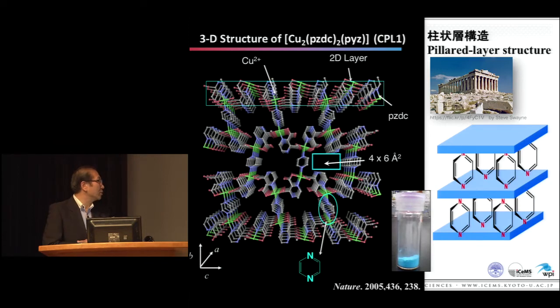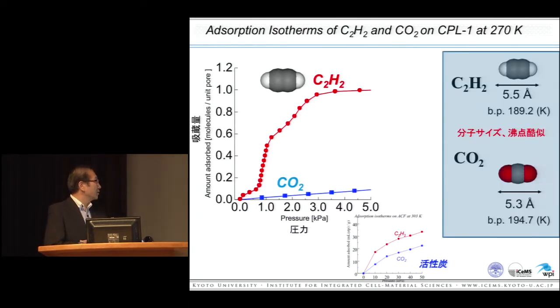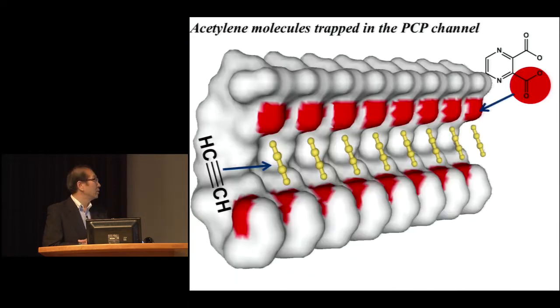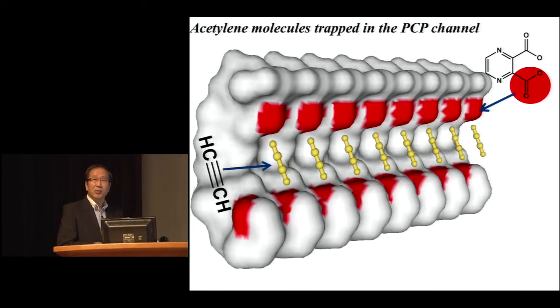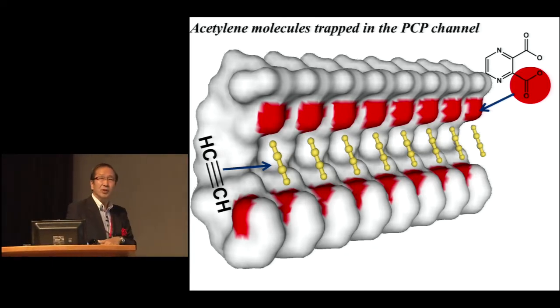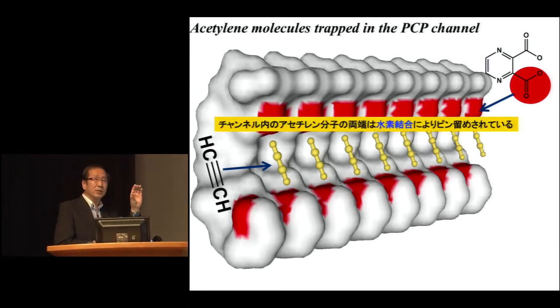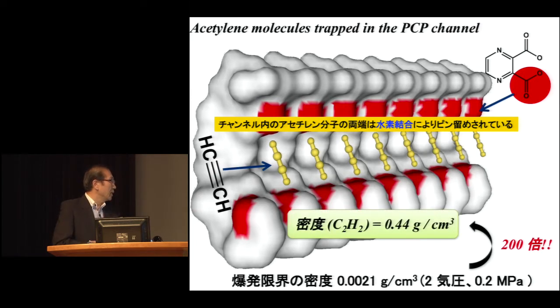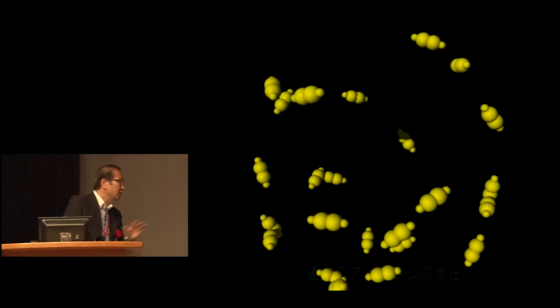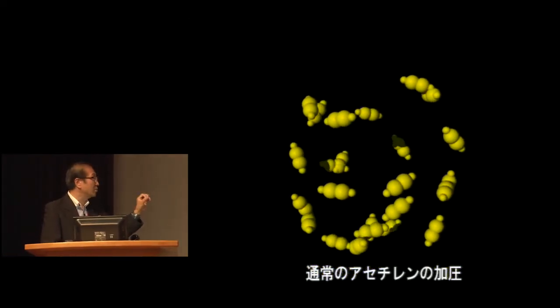This is the pillar layer structure we used to store acetylene more safely. That is the crystal. This is pressure by amount absorbed. The structure is very similar between acetylene and CO2, but only acetylene can be absorbed because of this structure. As you can see at the cross section of the pore, there are double hydrogen bonds. The hydrogen bond which can be seen in water. So double hydrogen bonds were used to pin down acetylene. Because of this bonding, they cannot react so easily. As a result, we are able to achieve a concentration 200 times the lower explosion limit of acetylene. When they come near, they tend to explode.